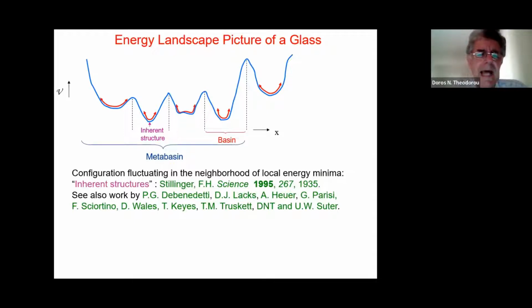Namely, we assert that a polymer glass is trapped in the vicinity of a local minimum of its potential energy with respect to its microscopic degrees of freedom. So this X here, which is represented as one dimension, is in reality the coordinates of all atoms that span the configuration space of the polymer. The potential energy is a very rugged function of this configuration, and it has many local minima. And the glass tends to be trapped in the vicinity of a local minimum or inherent structure, executing vibrational motions within a basin that surrounds this local minimum.